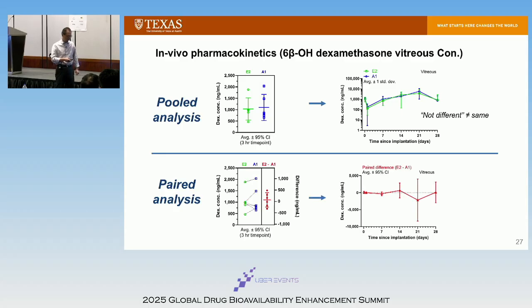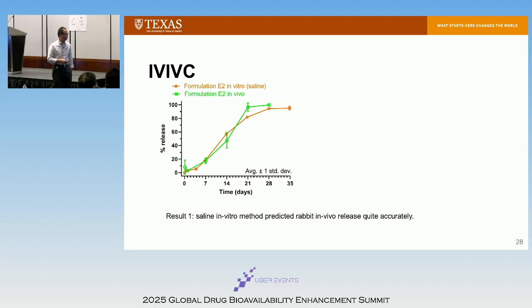And statistically, they're not really different, and the difference is within the confidence interval, except this 21 days. But we're only doing a group of 6 rabbits. And we think if the group size gets bigger, there's probably not much difference, okay? And what's really interesting is in vivo, in vitro release-wise, normal saline actually is a better predictor for the in vivo release, even though it's not bio-relevant because the vitreous environment is pH 7.4. Okay, but release-wise, they match up really well.